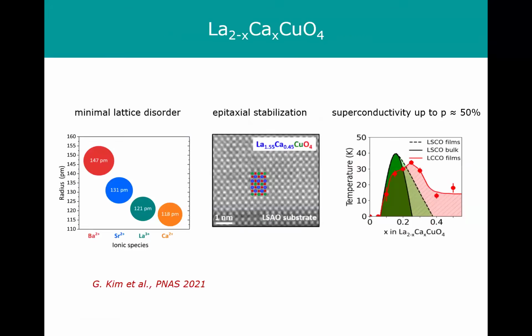Lanthanum calcium copper oxide is interesting because just looking at the ionic radii of the different ions that you can use to substitute lanthanum in the 214 system, calcium is by far the closest to lanthanum. So just from the ionic sizes, there should be minimal lattice disorder compared to strontium and barium. Now, unfortunately, lanthanum calcium copper oxide is unstable in bulk form.